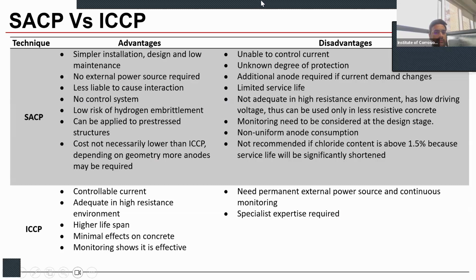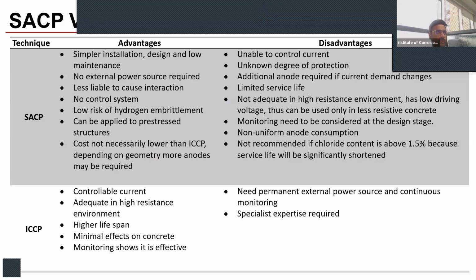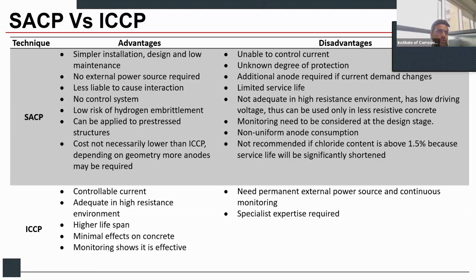However, the disadvantage is we are not able to control current, because the SACP system depends upon the potential difference between the steel and the anode. So once installed, we can't control the degree of protection we have to achieve. Additionally, anode current demand changes, so they have limited service life. They're not adequate in high resistive environments, have low driving voltage, so can be used only in less resistive concrete. Not recommended if chloride content is above 1.5%, because service life will be significantly shorter.